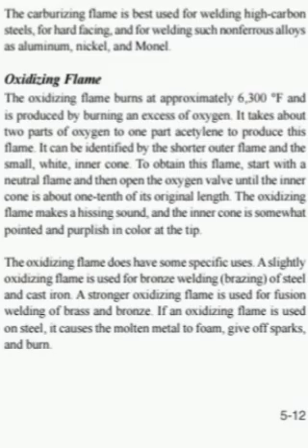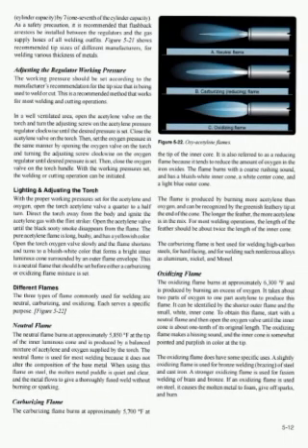The oxidizing flame does have some specific uses. A slightly oxidizing flame is used for bronze welding of steel and cast iron. A stronger oxidizing flame is used for fusion welding of brass and bronze. If an oxidizing flame is used on steel, it causes the molten metal to foam, give off sparks, and burn.